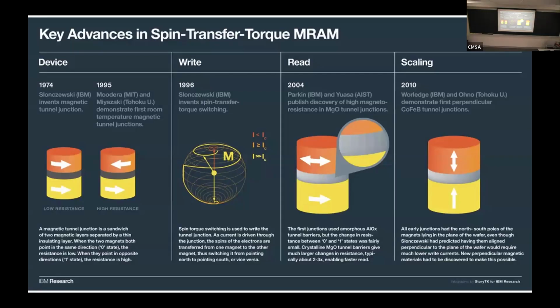stolen from our friends at IBM Research. This is talking about magnetic random access memory. And the key idea for this slide is that advances in materials drive technological innovation. So in the 70s, this idea for MRAM was developed at cryogenic temperatures. So I think at liquid nitrogen, 70K or so, I'm not exactly sure of the temperature, but cryogenic, well below freezing. And so the idea is you can encode bits, ones and zeros, with spins parallel and anti-parallel. It took 20 years to have this kind of device at room temperature, and many more years, with advances in the tunnel junction of the device, to have better read speeds, and spins going from in plane to out of plane to have improved write speeds.